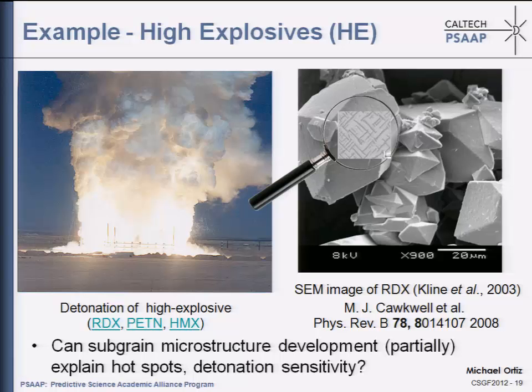And so the particular application concerns detonation of high explosives. In particular, what one wishes to understand is initiation sensitivity. So what is initiation sensitive to? And so the standard picture there is that, again, this is a multiscale problem in the sense that these HE materials have a grain structure, and then molecular dynamic simulations and also direct observation shows that at the subgrain level, the material develops microstructure.